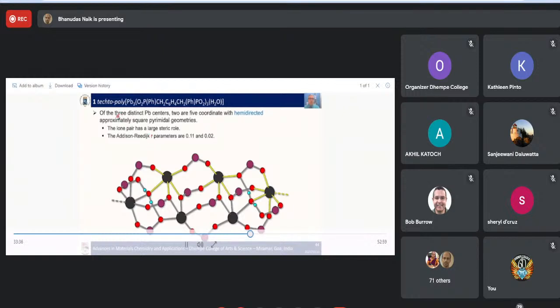In this compound here, you have 3 distinct lead centers. Two are 5 coordinated with hemidirected structures, approximately square pyramidal. You can see this one here and this one here. So the lone pair has a large stereochemical effect, and this one going off the side is about 5 coordinate here. So this one has a sort of vacant trigonal bipyramidal geometry.